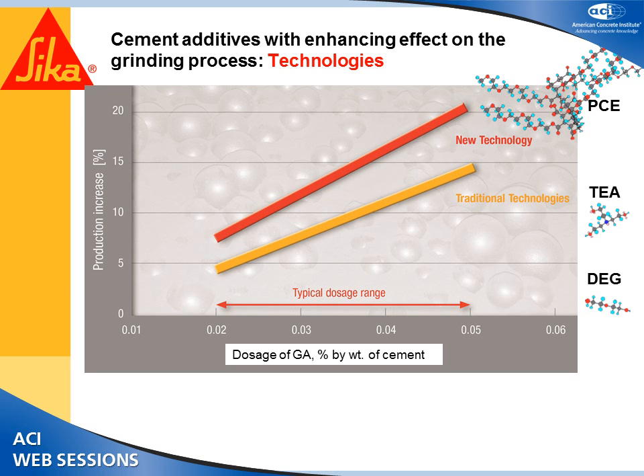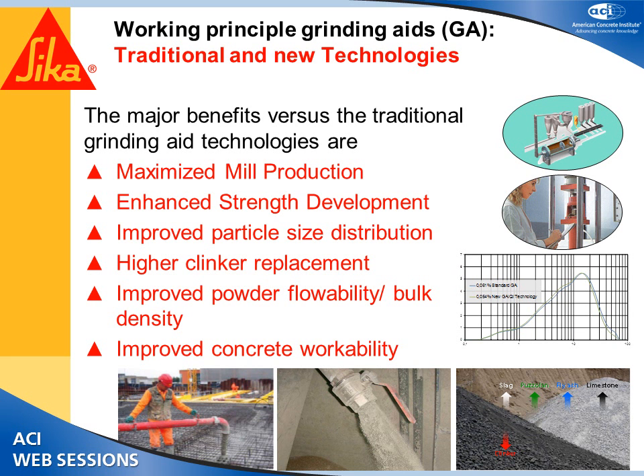With some of the cements, even if you use the traditional technologies, you can only get a certain performance. Even if you increase the dosage, you can't go beyond. But using PCE based, you can get much higher performance. So the advantages of using PCE grinding aids compared to conventional are maximized mill production, enhanced strength development, improved particle distribution, higher clinker replacement.